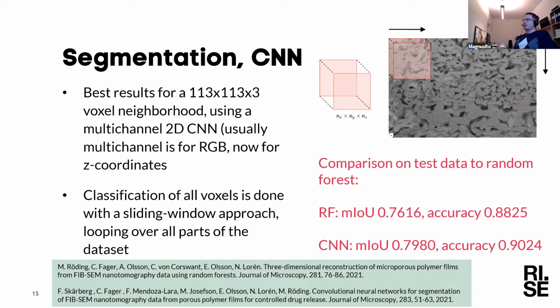And I think the explanation might be that since this is not the standard data that you see in the literature, where often you have 2D data with RGB channels, here we have channels which do not correspond to RGB, they correspond to Z coordinates instead. So this being a relatively different situation, we don't really know what the state of the art is. But what we found for now is that this is the best of the approaches that we have investigated. So we see that we get a little bit of accuracy increase, a couple of percent in the test data, from the random forests to the CNN.